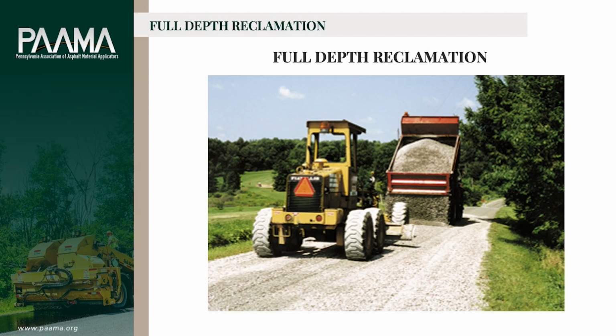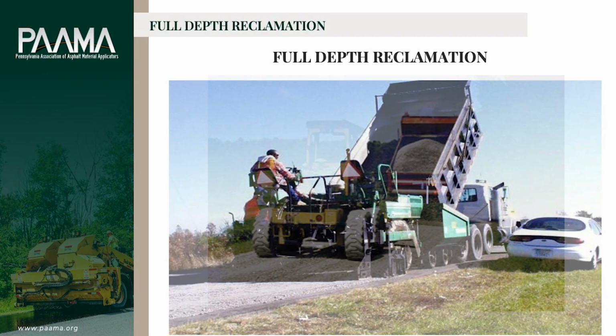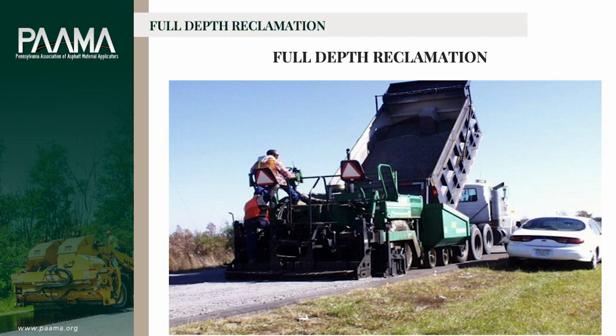And you'll see down at the bottom there, you have Highland Road, I think it says. But you have FDR depth of 8 inches, and the application rate's 33 pounds per square yard of Portland cement at that 8-inch depth. So when you're doing just the pulverization of the roadway, you could bring in extra aggregate, place them, grade them, or paver-lay them, and then you would mix all those materials together and it becomes a drainage base for whatever you're building on top. I talk with my hands, so look out.